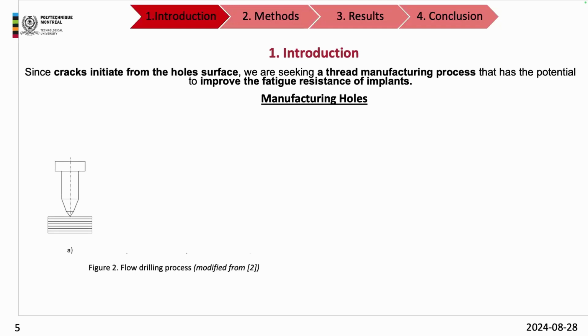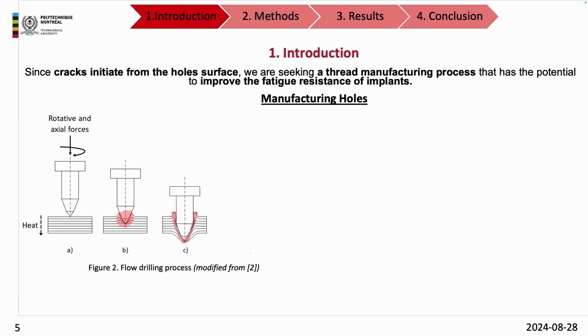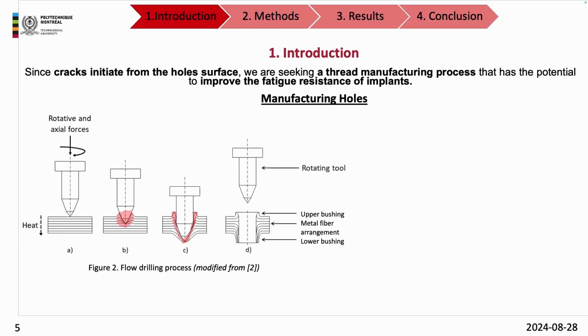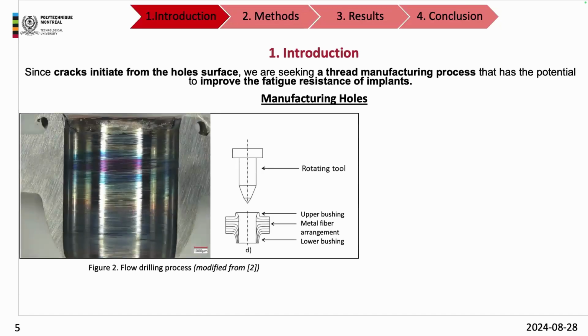One solution is to change the way that we drill the implants. The proposed solution is the flow drilling or the friction drilling. It consists of a rotating tool with axial force applied on it in order to create friction, and this friction will heat the material, not until approximately 700 Celsius degrees, allowing the tool to penetrate the material. And then when we remove the tool, we have a new hole. This hole has specific features such as an upper bushing, a metal fiber rearrangement, and a lower bushing, but it's not what we're interested in today.